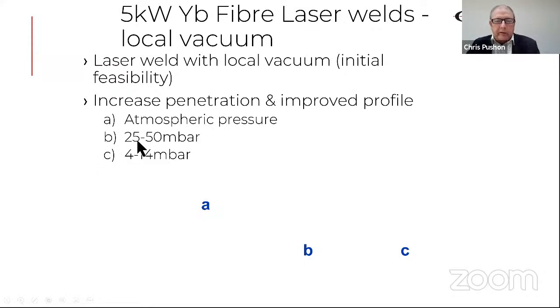And what we've discovered is that if you weld at this pressure, you double the penetration of your laser weld. So with a 5 kilowatt laser, we were welding about 10, 12 millimeters. By going to this pressure, you double that to about 20 to 25. And with the added benefit that you don't need any plasma suppression gas. And with the additional benefit is there's no weld porosity or cracking.